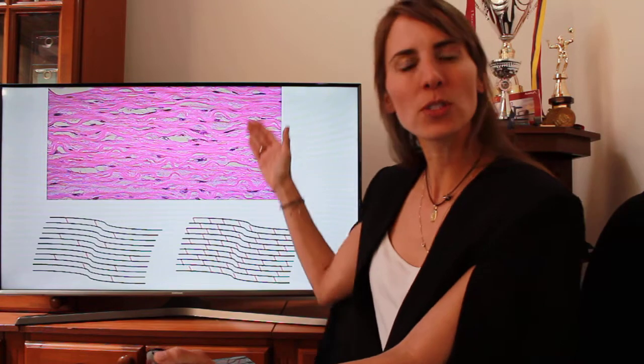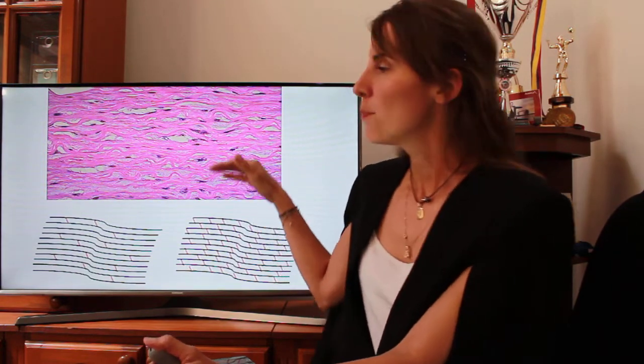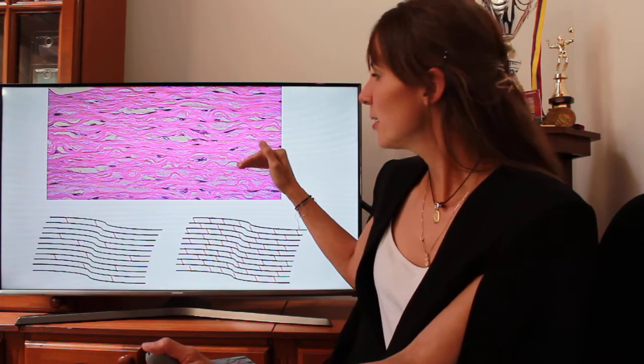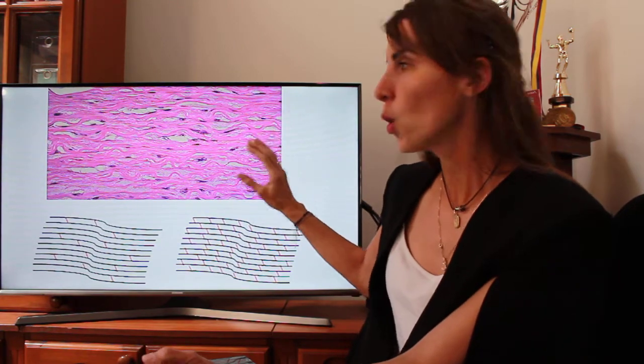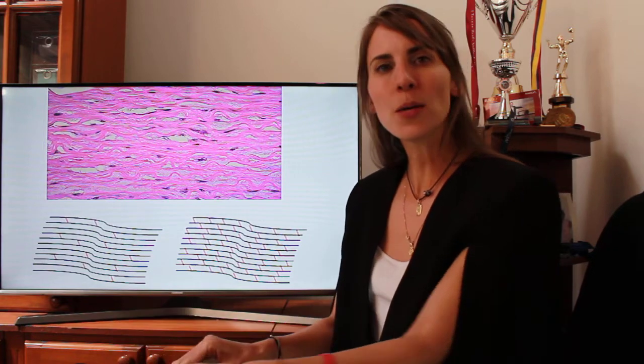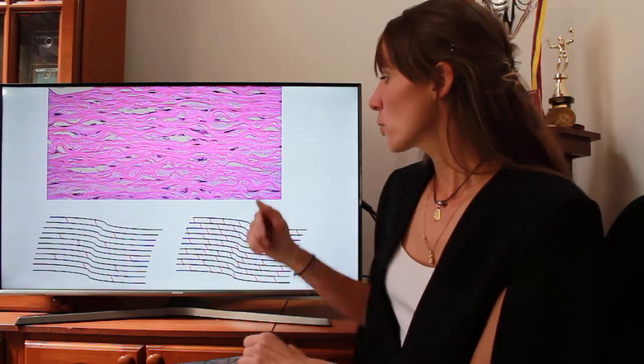What you see here is a normal structure of collagen made by horizontal fibers of collagen and cells that are inside of this structure. This is a microscope view. So when we're going to produce a membrane or a scaffold, we have to separate these fibers, after this we have to clean the immunogenicity, and then we have to put it together again. We do this through chemical cross-linking or other mechanisms, or through sugar cross-linking.